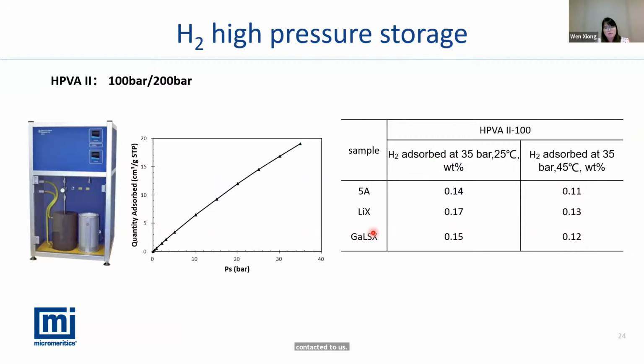The last example I want to show on the adsorbent and membrane solution is high pressure adsorption. The HPVA I mentioned earlier, here is an example of hydrogen storage using HPVA to check the storage capability at high pressure. We looked at 3 different kinds of materials at 2 different temperatures, and checked the hydrogen storage capability at 35 bars. That's the results shown on the right. The middle figure is the adsorption isotherm, quantity adsorbed versus pressure, which is high pressure in this case. Now I'm done talking about the adsorbent and membrane solution.